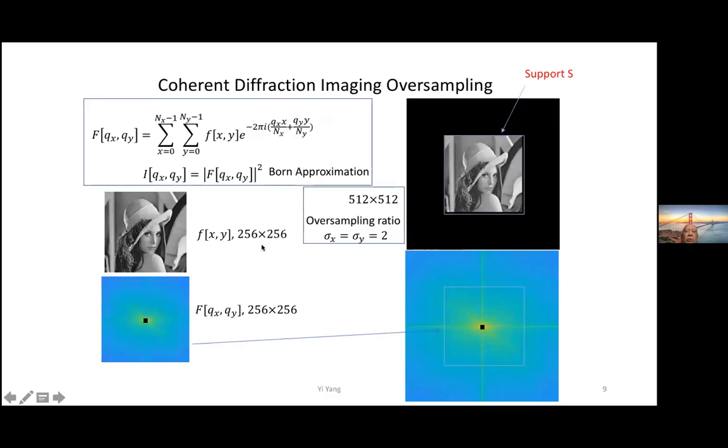There's also the question of oversampling, which means that you have to make sure that you've got enough Q points to make up for the lack of phase information. So if you measured the intensity at n points, you need to measure at 2n points to get the phase as well. You've got n amplitudes, but you don't have n phases.